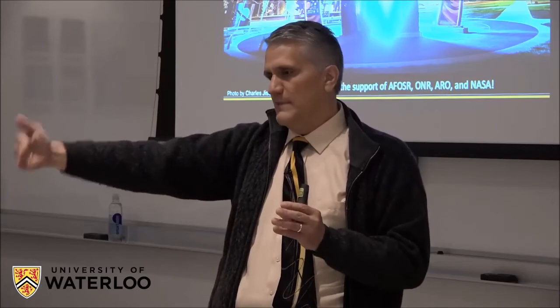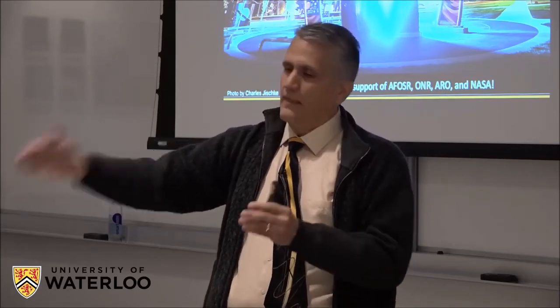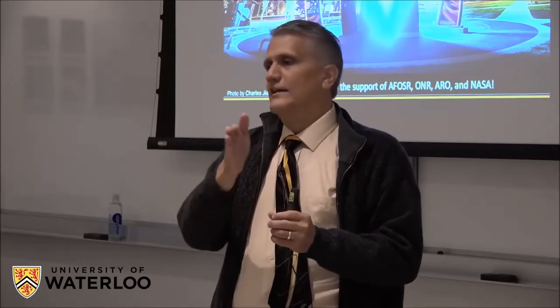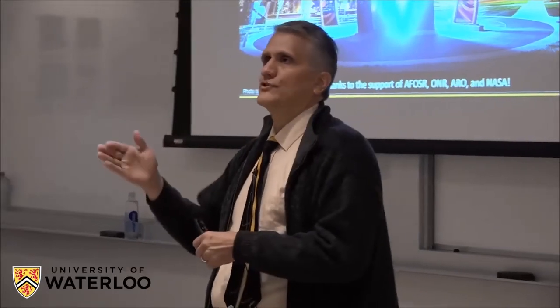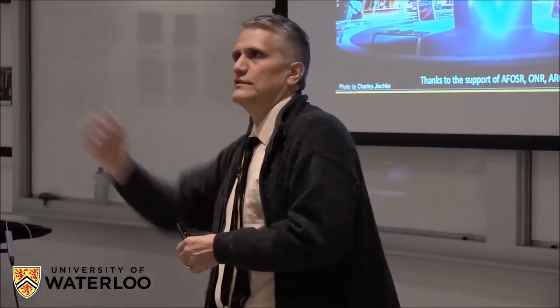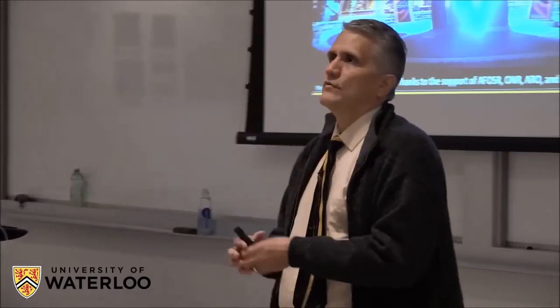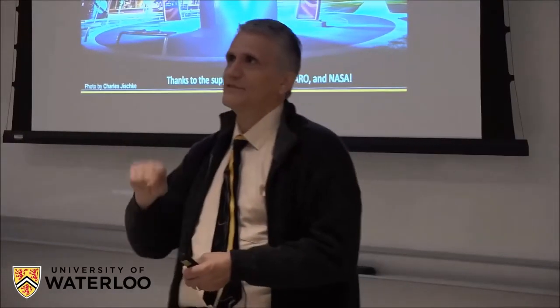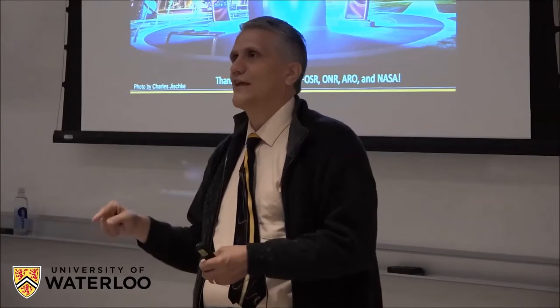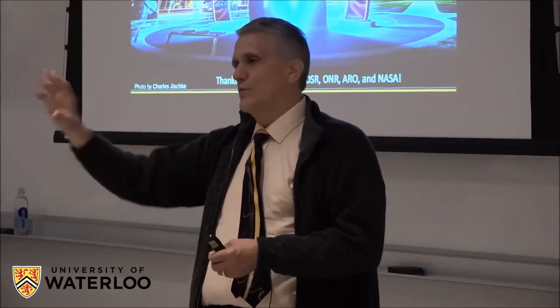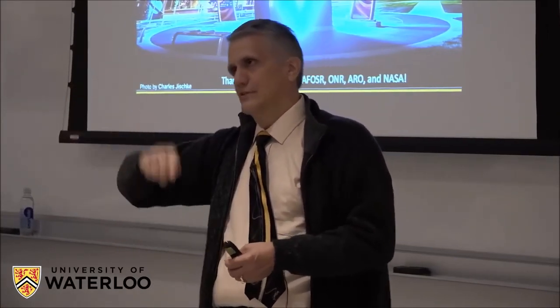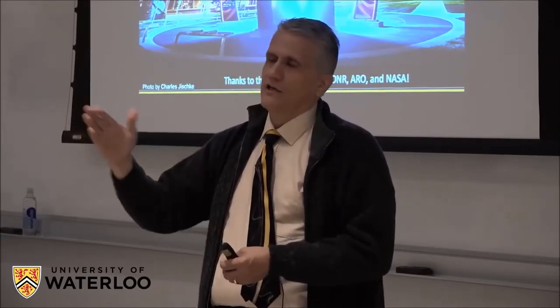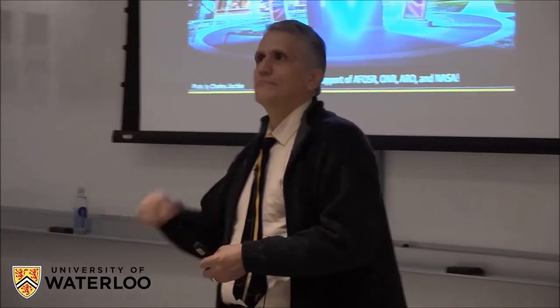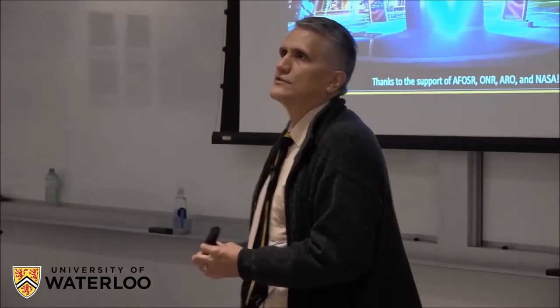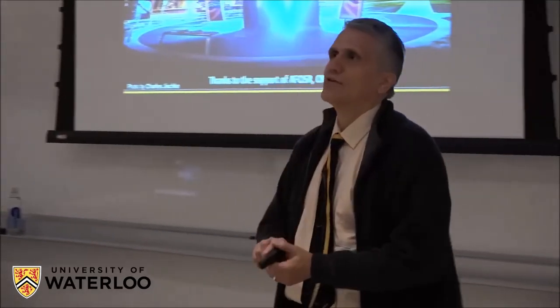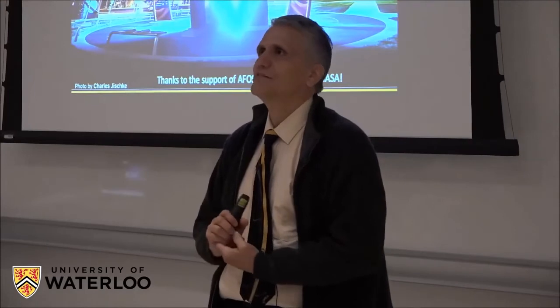We know where our limit is on the time of milling and so forth. And then we back off from that a lot, and then we look at how much of that material is reacted as we change the milling time or milling parameters. We use a DSC/TGA, differential scanning calorimetry and thermogravimetric analysis, to see what we are doing in terms of the onset of exothermicity, and are we cutting into the energy by this premature oxidation? So you have to watch that very carefully, and it's a safety issue as well.